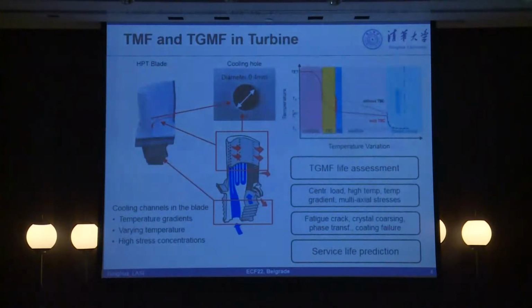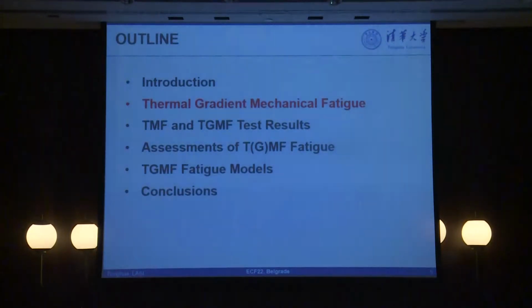Right now, most engine makers just use the isothermal method to design components, since we believed the fatigue property of material at higher temperature should be worse than at low temperature. That's what we believe. The situation could be slightly different. There's much research published in the past years. They found that the thermomechanical fatigue property of material can be much worse than the isothermal high-temperature fatigue property. Therefore, it becomes a problem how to quantify the effect of the thermomechanical coupling. Additionally, we have in the case the so-called temperature gradient. We introduce thermal stress into the component, and how to quantify the effects also becomes a severe problem. That is the motivation I want to tell you.